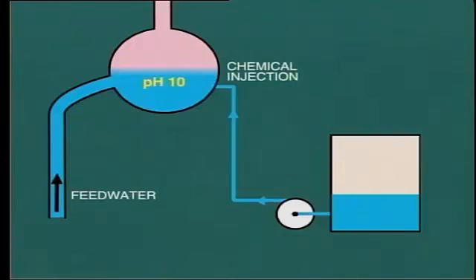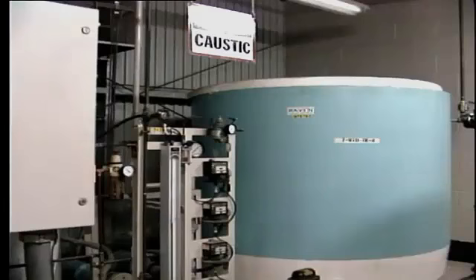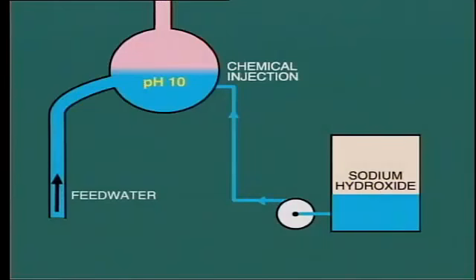This is done by injecting sodium hydroxide. This is a highly alkaline, caustic solution. Similar to the case of phosphate injection, a mixing tank and high-pressure feed pumps are provided to inject the caustic directly into the boiler drum. This injection of caustic does achieve the objective of raising boiler water pH value, but it also has some negative effects. One is that we are adding yet more solids to the boiler water.